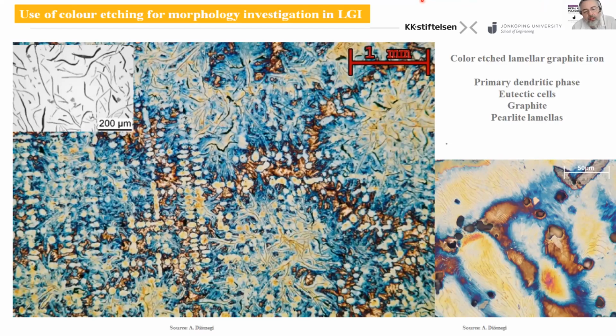So I'm going to present a couple of slides here. This is a color etched lamellar graphite iron, and it's very interesting to see that in the same picture you can see both the primary dendritic phase and the eutectic cells interfering with the graphite, and with a little bit higher magnification you can also see the pearlite lamellas. So practically you can see everything in the same prepared sample, except the austenite grains, which is another matter of technology to prepare.